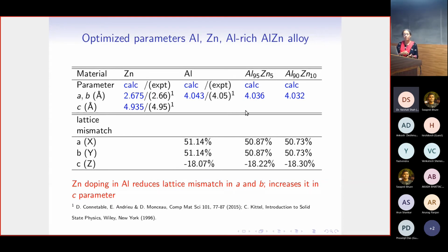Now if I dope it with zinc, then based on what is the amount of dopant we have, this lattice mismatch changes. And because for zinc we know A is much smaller than the A of aluminum, doping we can understand is going to reduce the lattice parameter for the aluminum rich zinc system. So we see that this lattice mismatch decreases. But this decreases, we have to keep in mind, in the A and B direction, but it increases in the C parameter. Okay. So now we have the bulk structure.